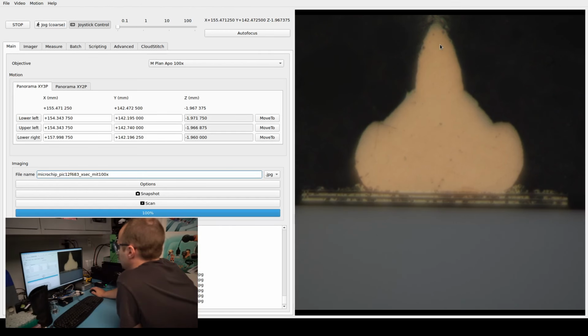And then looking up towards the top, we see the main diameter of the wire, and below that is the deformed area where the ball was squished out and flattened. This right here is the inside diameter of the needle, and so we can see that as the needle pressed the ball onto the pad, it squished out to the sides and then also squished up a little bit inside the needle.